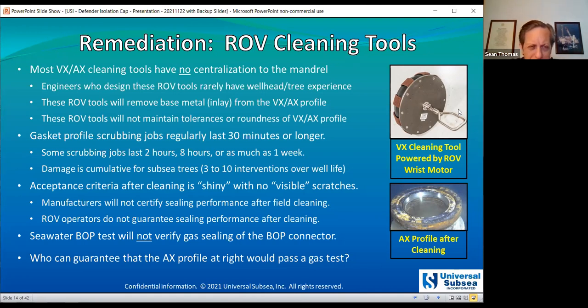We've heard many field reports of these scrubbing jobs lasting more than 30 minutes, up to 2 hours, up to 8 hours. And there's one field report where they scrubbed on one tree for an entire week. And of course, the damage is cumulative. So for the subsea tree especially, you'll have multiple interventions over the well life. You really want to minimize how much scrubbing you do on that gasket profile.